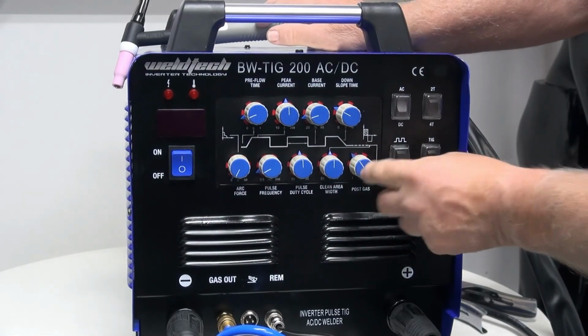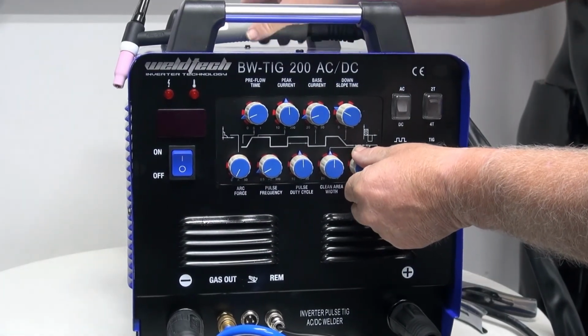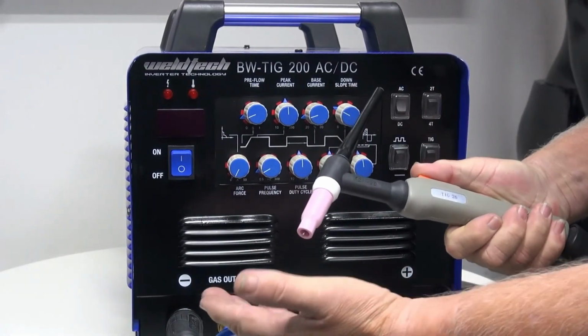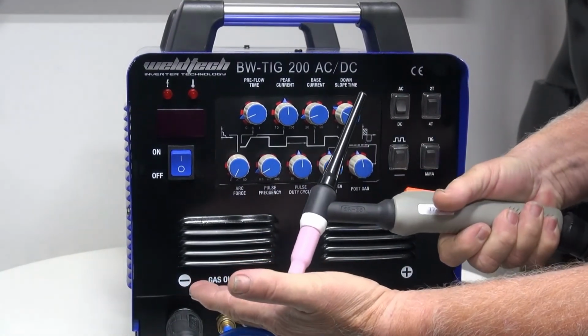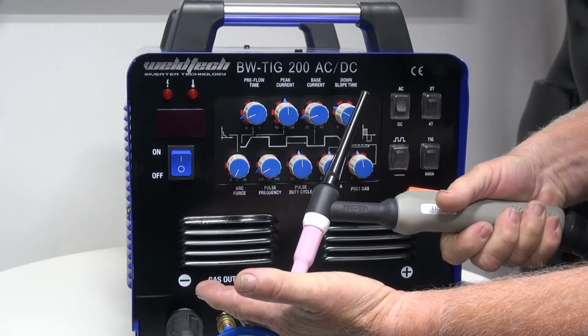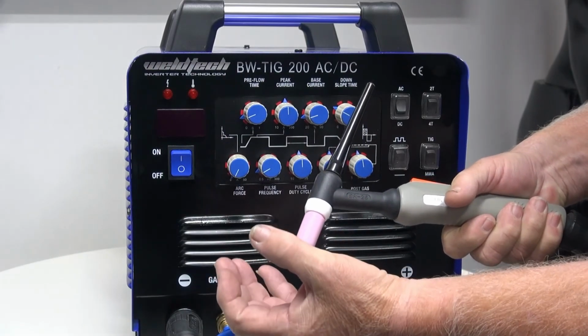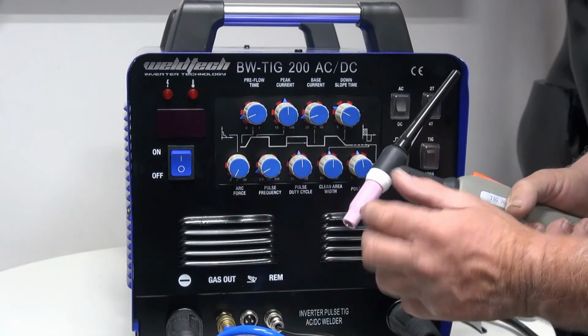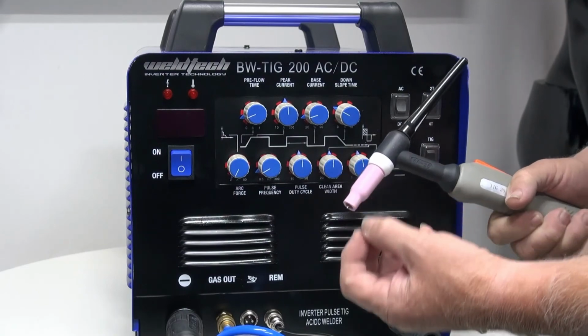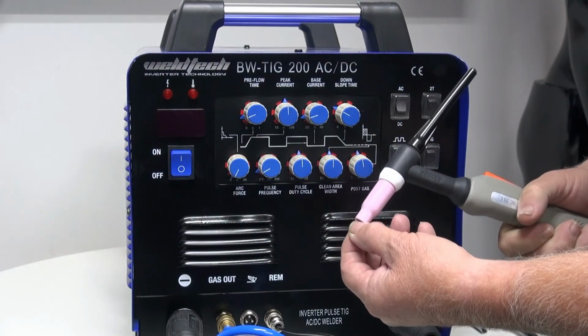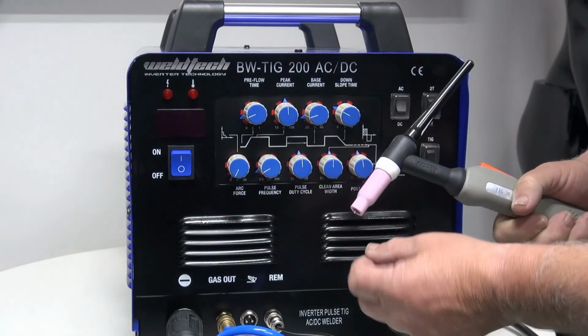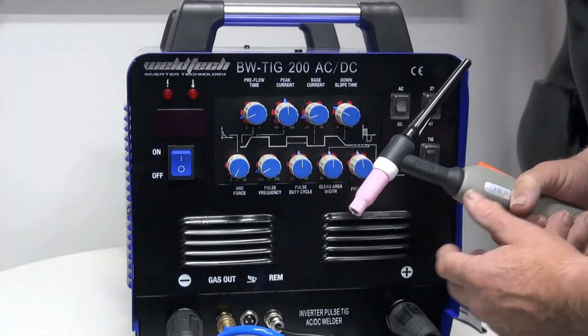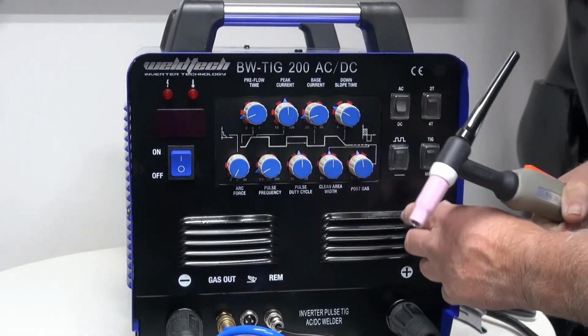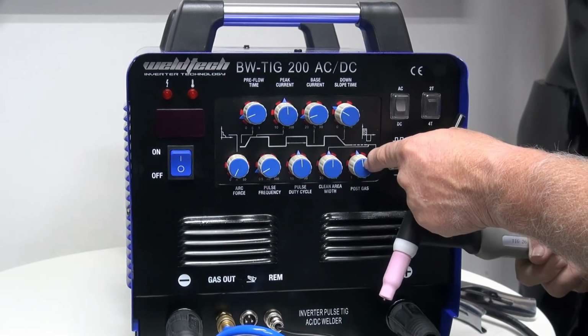The last knob we're going to look at is post flow. When I let my trigger go and wind down, the arc goes into downslope, and then the arc stops. The gas will keep going. This is to stop the tungsten from oxidizing. If you have an oxidized tungsten, you get a bad restart. The other thing it stops is oxidization of the weld pool. It's a very, very important knob that people forget.